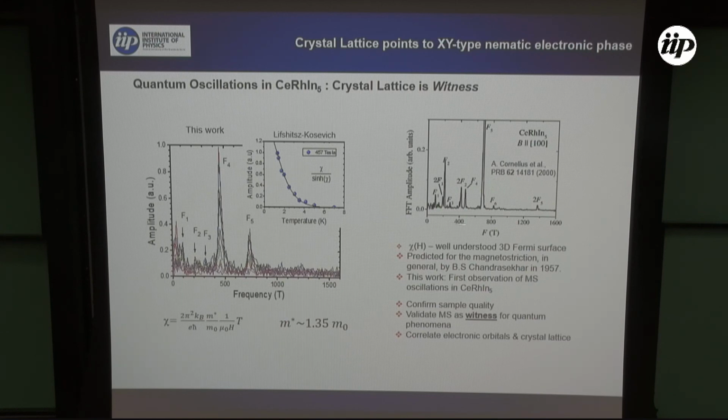Let's see, there's 400 here, there's a 400 here, this one here, etc. But the intensities are different, and that means that different wave functions couple strongly or less strongly with the atomic positions, right, with the localized moments. So magnetostriction and magnetization give you slightly different information on which orbitals participate in the lattice bonding. So this is information that you can potentially use to simulate or to calculate the properties of this material.